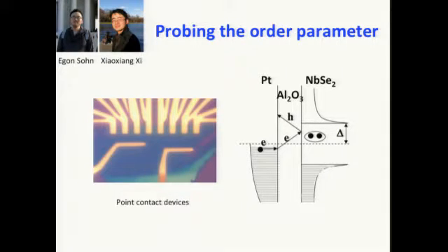So we would like to measure the order parameter in our material. This is a schematic of our device. We've put many points so that if one junction breaks, we can still measure the other junction. We use platinum as the electrode with a thin layer of aluminum oxide, and then put the material directly on top of these many electrodes.